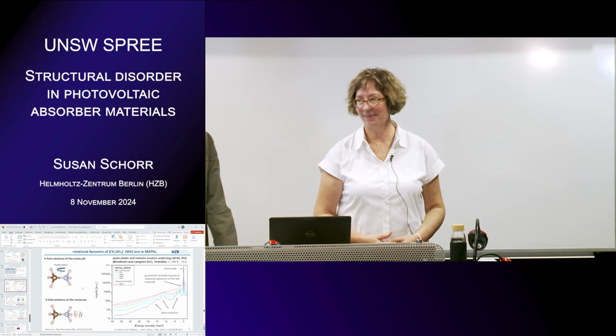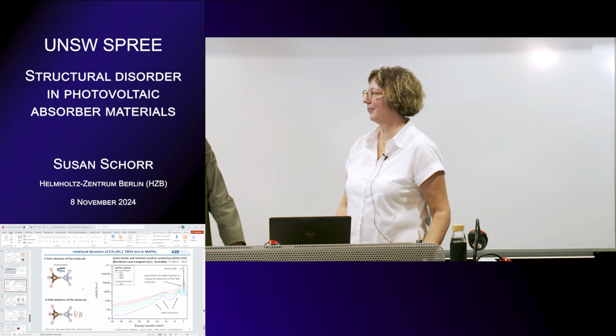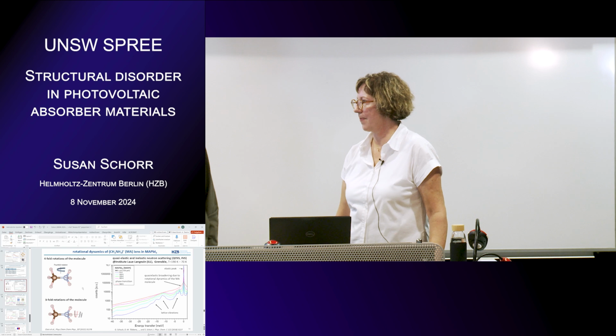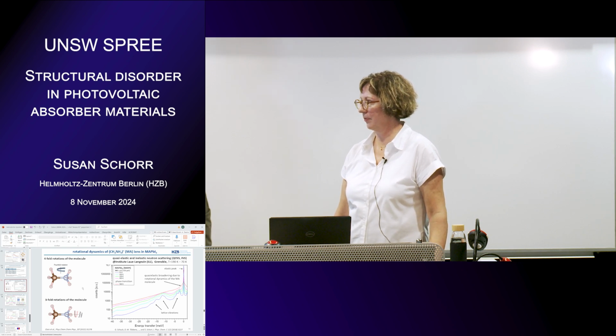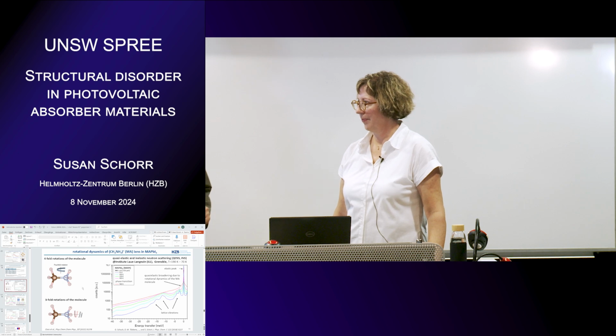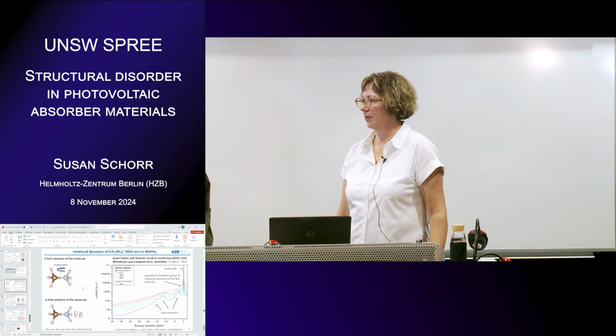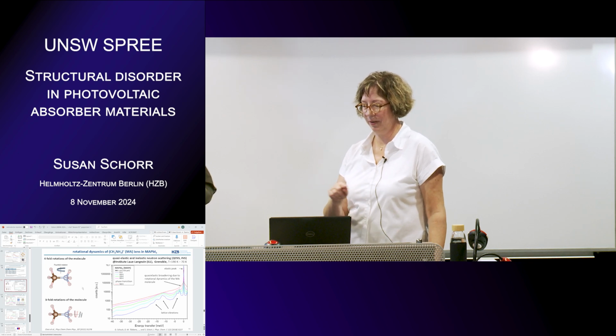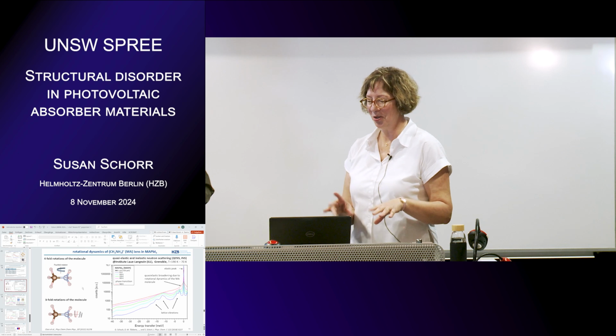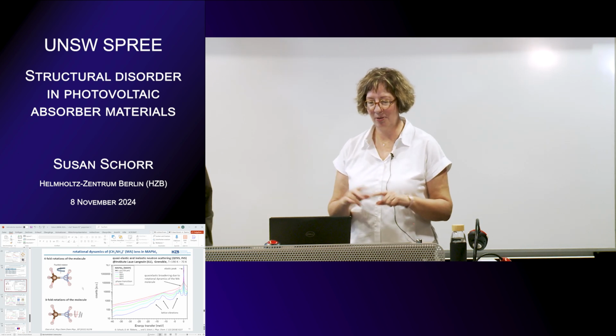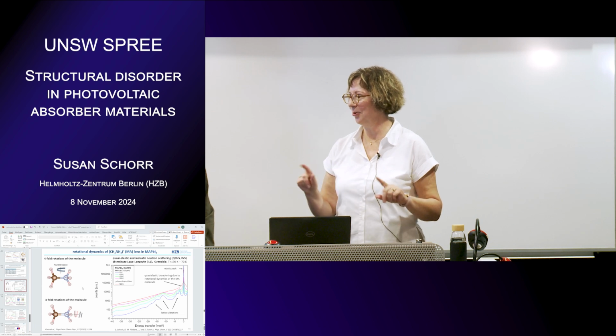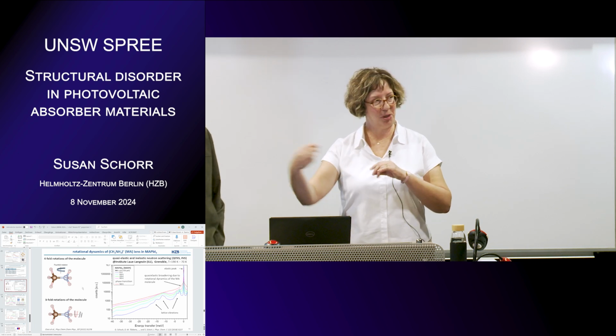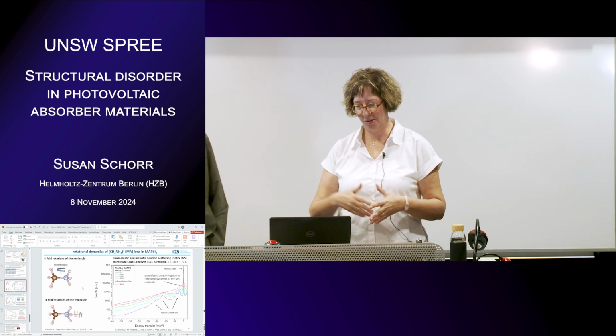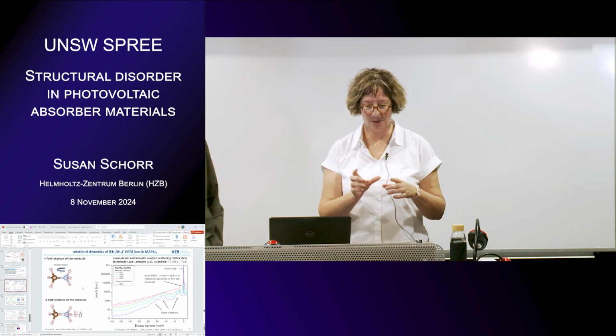Thank you. I have a follow-up question. Does that mean for your neutron scattering analysis, if the composition is the same, you believe that the defects should be similar? Yes. No matter what kind of method you use to achieve the material? As long as it is homogeneous. These considerations from the off-stoichiometry type model are purely crystallographic considerations. It has nothing to do with chemistry, only with which direction you go in the phase diagram. That's why you can calculate it easily from your solid solution formula.